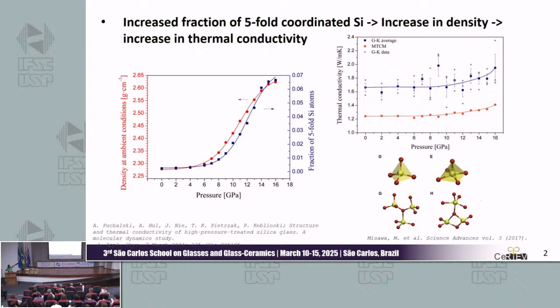And this you can see on the first figure: the density in ambient conditions increases, and so does the fraction of 5-fold Si, up to around 0.07. And this is the main mechanism of densification in glass. There is no change in intermolecular distance. On the second figure, you can see the thermal conductivity, obtained by the Green-Kubo method in the simulations. You can see a small increase with the highest pressures. And this generally follows a model of minimal thermal conductivity.